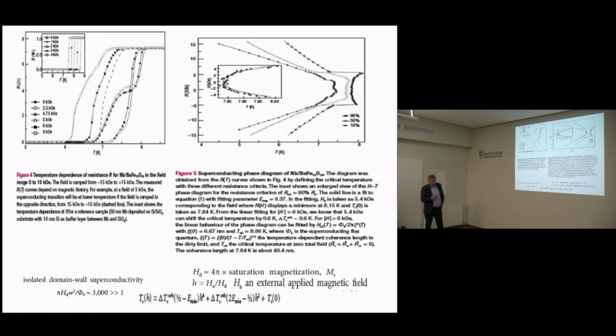Now, let's have a look at the transport measurements. In this figure, we see two types of curves. In this inset, we see the niobium film deposited on this single crystal and on silicon. On silicon, the resistive transition behaves as one can expect: with a larger magnetic field, Tc is shifted to lower temperature. And non-monotonic behavior is seen on this heterostructure. First of all, in zero magnetic field, we see some transition. Now, if we increase the magnetic field, the curve is also similar.